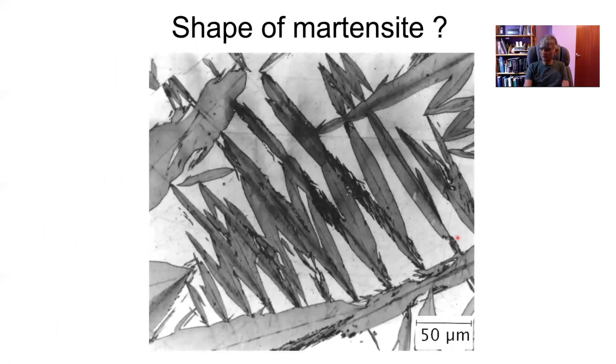And I mentioned that we need to explain the shape of the martensite, and we'll do that as soon as we are able to calculate the strain energy of transformation. Now, given that you produce the structure of martensite by a deformation of the austenite, the parent phase, we expect a close crystallographic relationship between the austenite and the martensite. And that relationship should be reproducible because each one of these plates is forming by the same mechanism. And indeed, when we measure the orientation between the martensite and the austenite, it is highly reproducible,